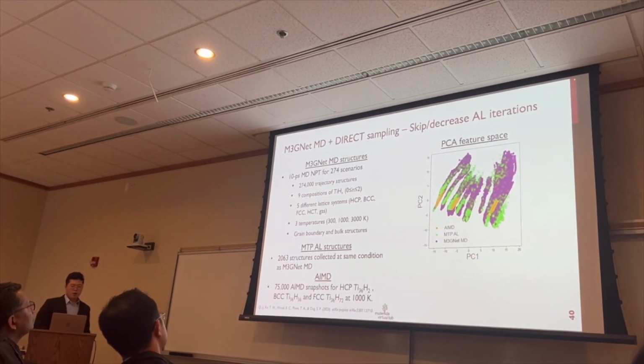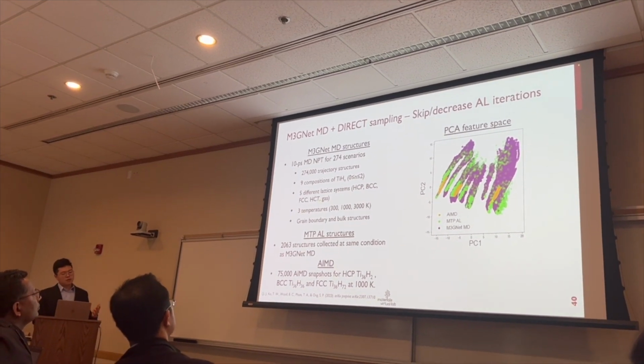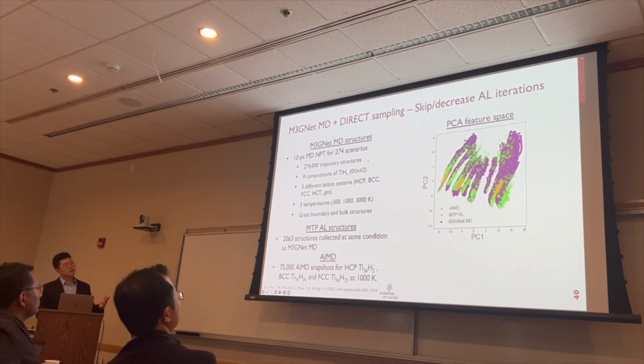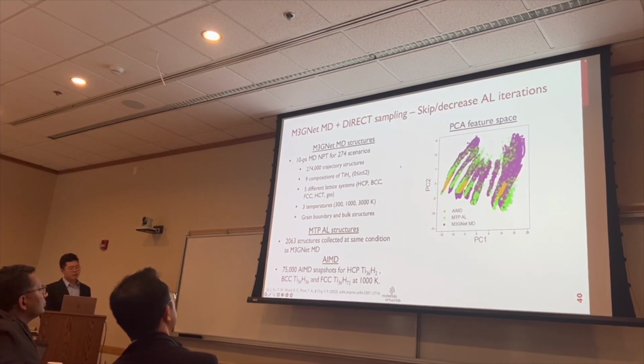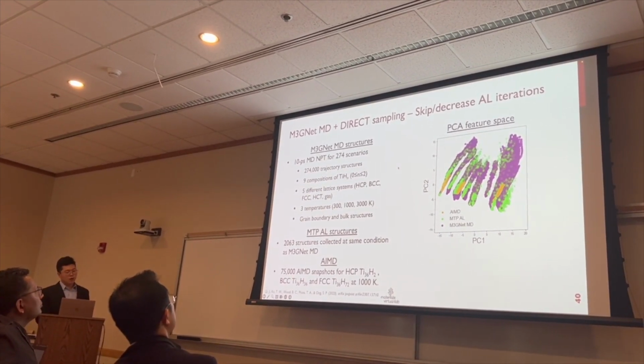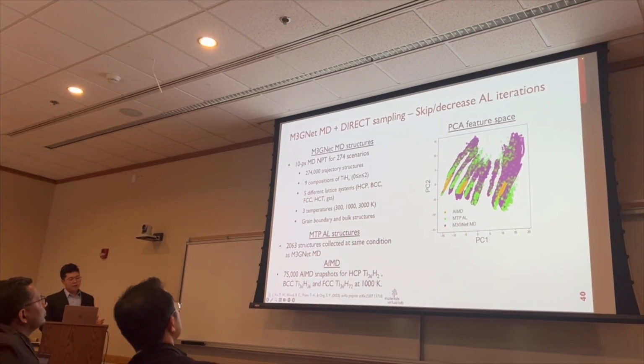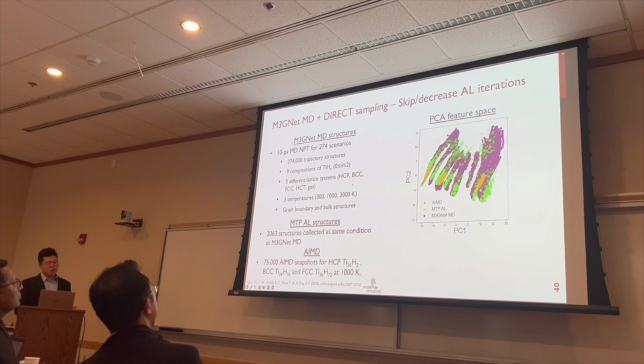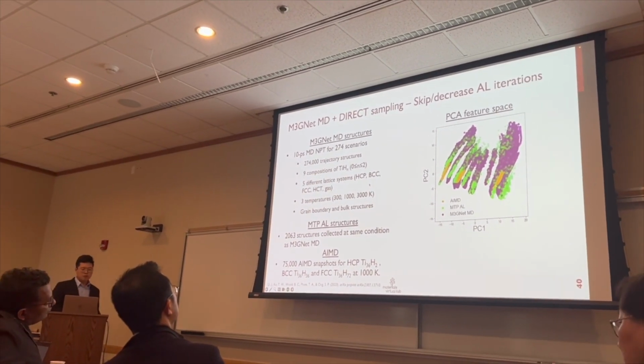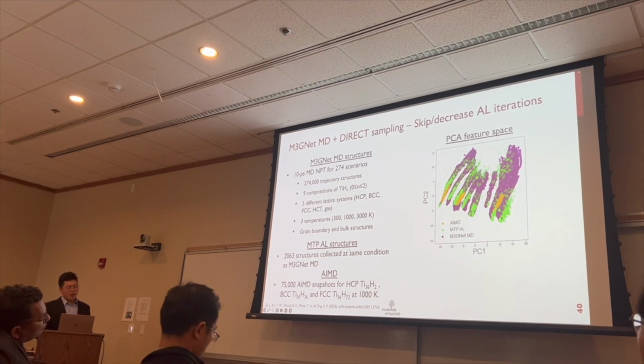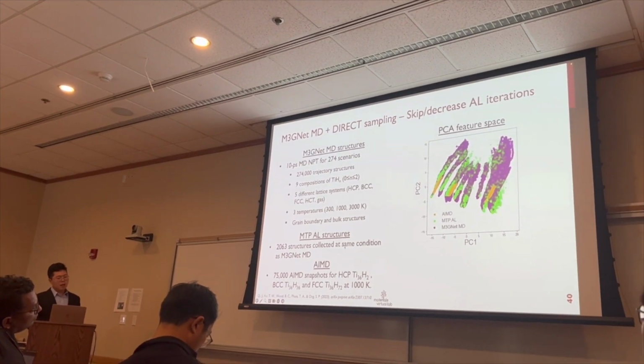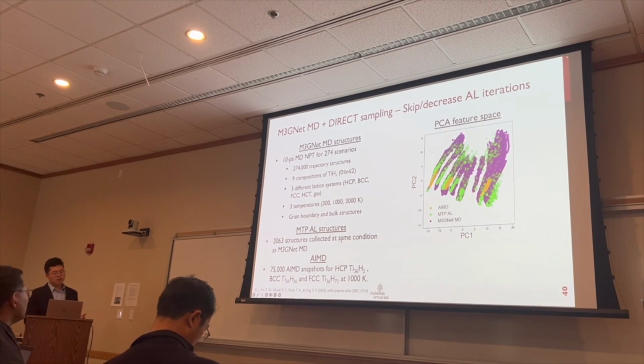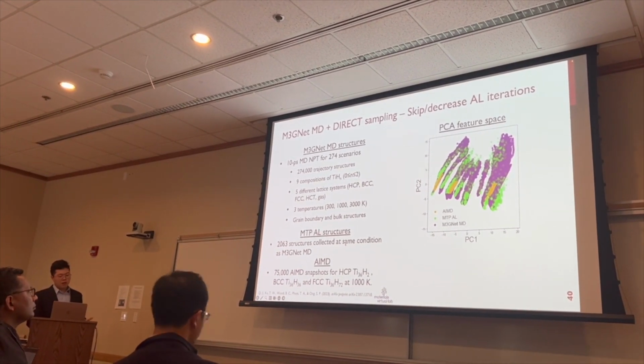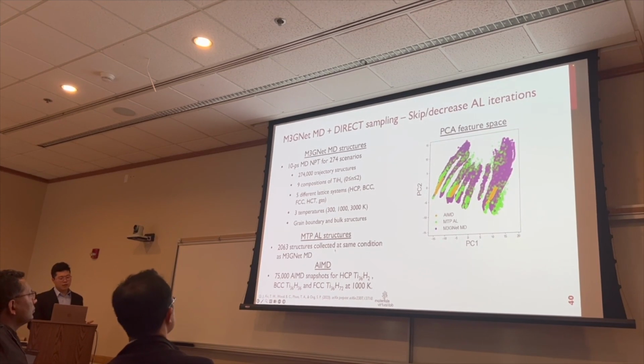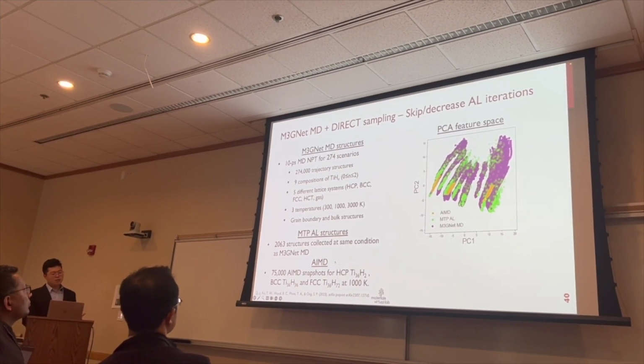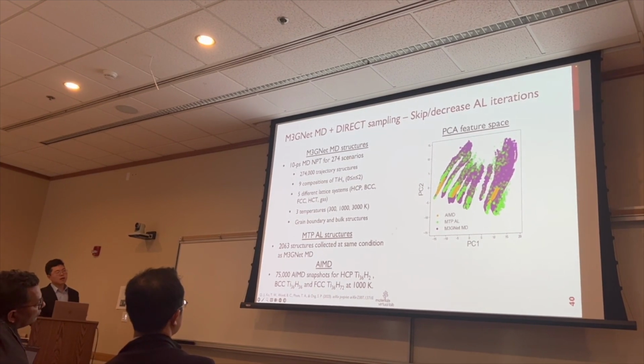In this case, we generate this structure set with M3GNet molecular dynamics for the titanium hydrogen system. There are in total 274 simulation scenarios of molecular dynamics, containing different lattice systems, different temperature ranges, and also different system types. We performed the MTP active learning on exactly the same 274 MD scenarios to collect the active learning training set. And the third set is an AIMD set that is done on some selected temperatures.